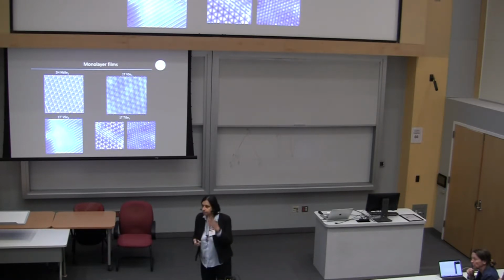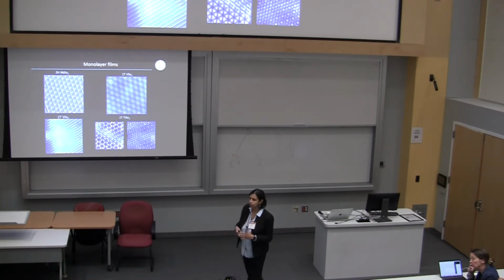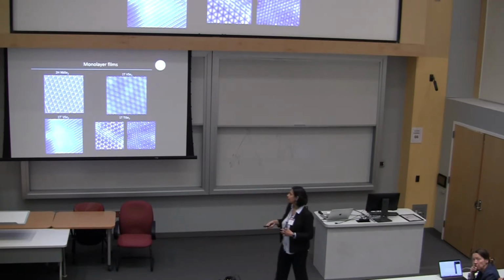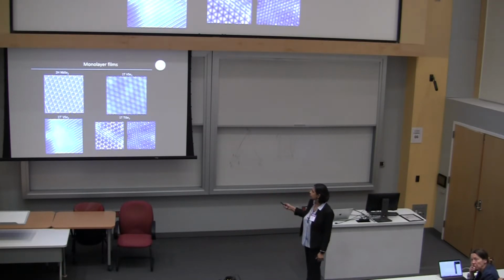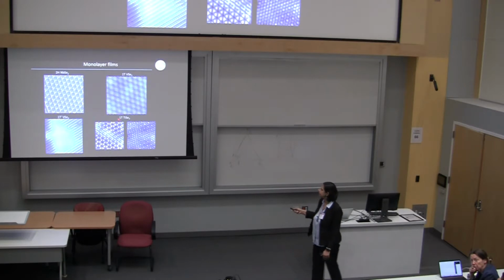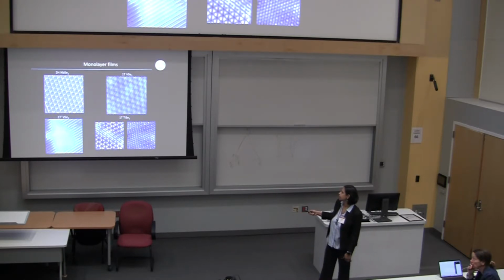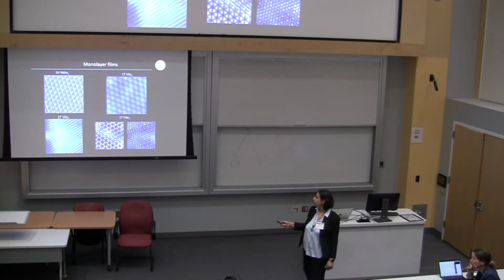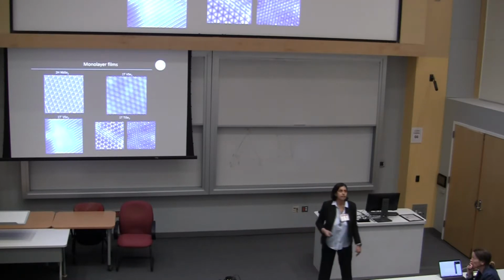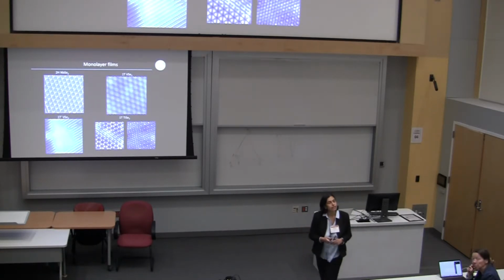Have you done like cross-sectional imaging to see if there's like a sulfur atoms maybe before you actually grow your layer? No, but we know the height. The height matches what we expect. So these are all monolayers, and here's titanium diselenide. It's shocking actually that the CDW survives. In all of these, it's really surprising that the CDW survives. Yes?